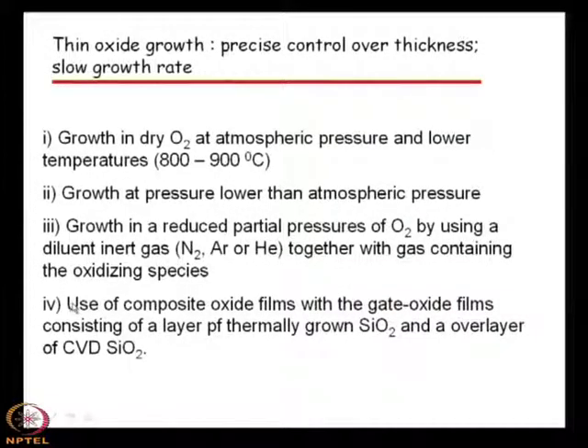Another process that can be used is composite oxide films, with the gate oxide film consisting of a layer of thermally grown SiO2 and an overlayer of CVD SiO2, meaning silicon dioxide made by chemical vapor deposition. So, these are the processes that can be used. There are many other processes people have reported, but mostly the industry has adopted this one, that is, growth in dry oxygen at atmospheric pressure and lower temperature.